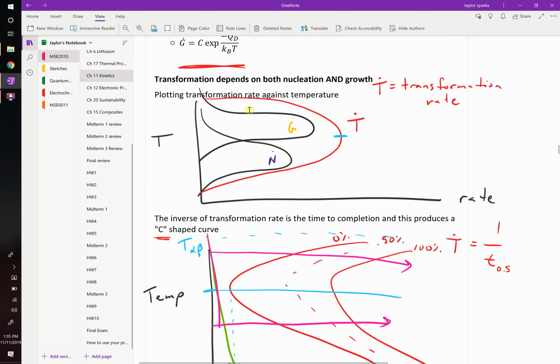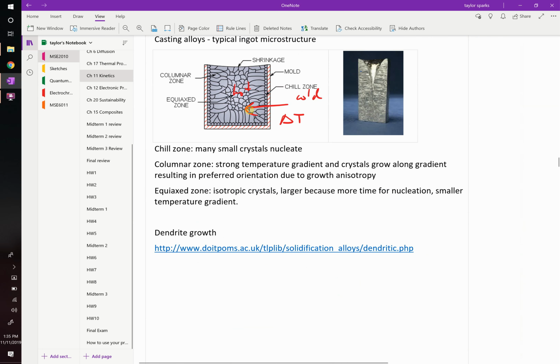Can you think of an application where you want a huge difference in strength, like anisotropy, in the middle of your alloy? Not typically. We typically want things to be more uniform than this, but if you pour it into a mold, that's what's going to happen if there's a temperature gradient. So because of that, people have tried all sorts of things to control the temperature gradient when you do this. And what that can lead to is the dendrite structure, dendritic growth, okay?